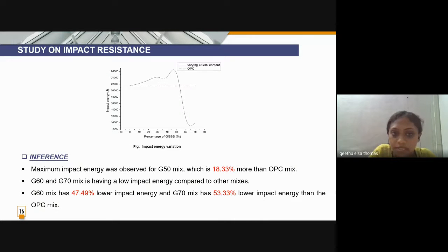This graph depicts the variation of impact energy by the addition of GGBS and replacing the cement, with the reference specimen being the OPC mix. From that, it is inferred that maximum impact energy was observed for the G50 mix, which is 18.33% more than the OPC mix. G60 and G70 mixes have low impact energy compared to other mixes. Also, the G60 mix has 47.49% lower impact energy, and the G70 mix has 53.33% lower impact energy than the OPC mix.